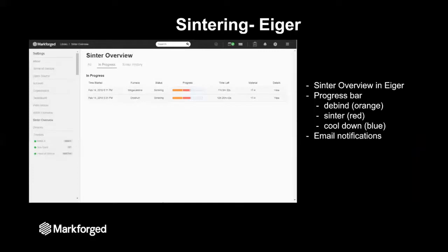Here you'll see the center overview portion of Eiger, and the most important part is the progress bars. The progress bar is divided into 3 parts. First is the orange portion, which is the debinding stage. This is when the furnace is heating the part and burning out what is left of the binder. After which it goes into the red portion, which is the center profile. This is going to heat that metal up even higher and make those metal powders actually densify together through the process of sintering. After which it enters into the blue portion of the progress bar, which is cool down.